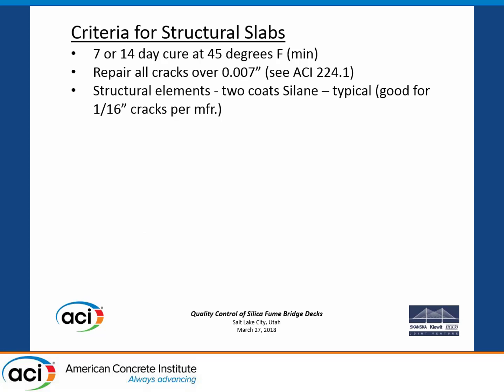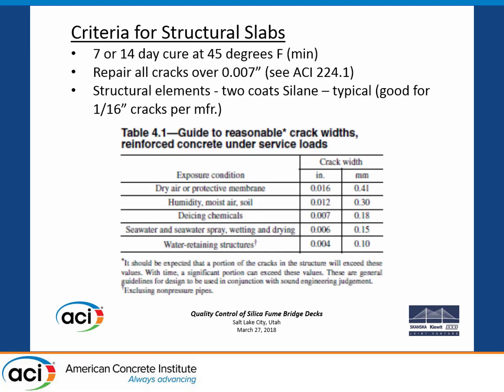We got either a 7 or 14-day cure. 7 days on approach slabs, slabs on grade, structural slabs on grade, 14 days on decks, all right? We have to repair any cracks over 7 thousandths. That's part of the deal. And then the structural elements, we're supposed to put 2 coats of silane. Now, the manufacturer that sells the silane, he says it's good for a 1/16-inch crack. That's 64 thousandths of an inch. But we have to heat seal anything over 7 thousandths.